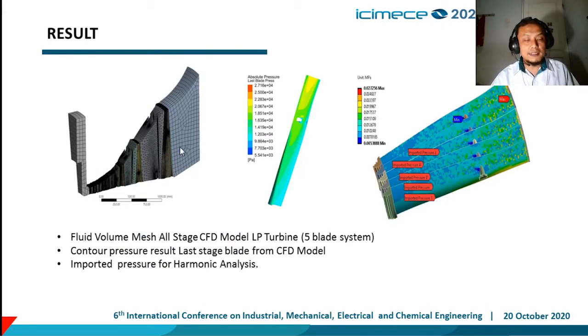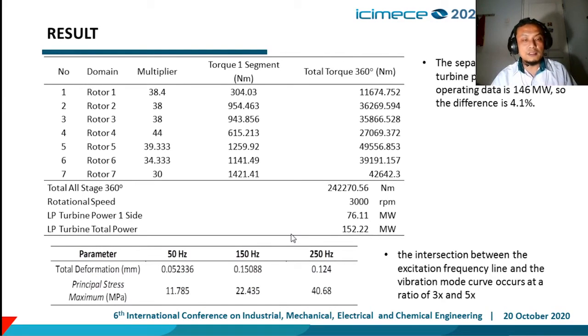So for stress evaluation, we are using a fluid volume mesh, an all-stage CFD model of the low pressure steam turbine blade, using a 5-blade system to reduce resources on the Ansys analysis. We took the pressure contour result of the last stage blade from the CFD model and imported the pressure for harmonic analysis. So this is how we do validation of the CFD model, with a calculation of turbine power from actual operating data and the CFD model. We got a difference of 4.1%.